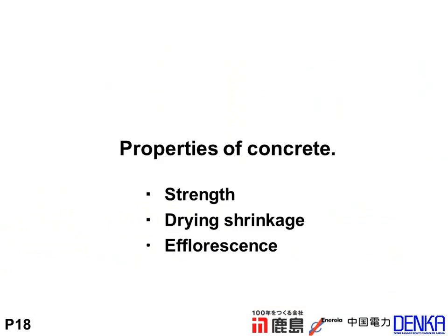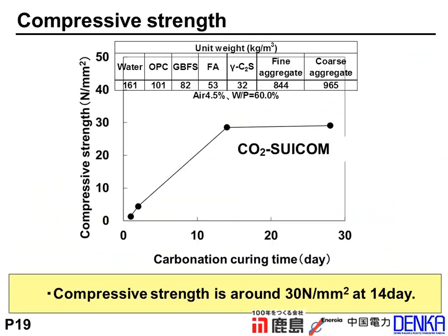Finally, I'd like to explain the properties of concrete, for example, strength, drying shrinkage, and efflorescence. This figure is the result of the compressive strength according to the carbonation curing. You can see that the compressive strength increased with the carbonation according to the carbonation curing. It reached around 30 Newtons per square millimeter at 14 days. The carbonation proceeds into the middle of the concrete specimen at 14 days. After that, the compressive strength did not change up to 28 days.